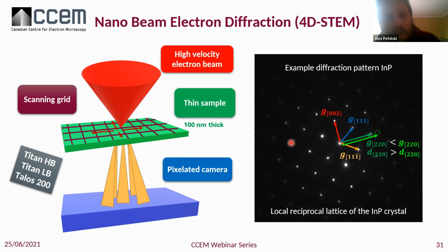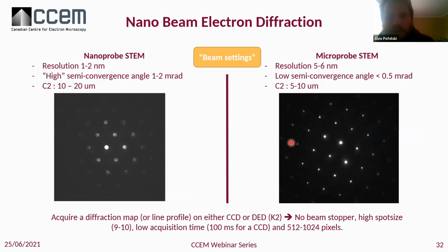But the gain here is that we are not limited now to imaging one unit cell. You can image a couple of unit cells at once, or you can even move the probe to a completely different location. So we are not bound by this oversampling condition anymore. So by breaking those, this is like the two modes that I propose to use for diffraction for the strain application. And these types of elements are found in beam settings whenever you are on the Titan HB, Titan LB, or Talos 200. And there are two modes that are specifically targeted, which are microprobe STEM and nanoprobe STEM.